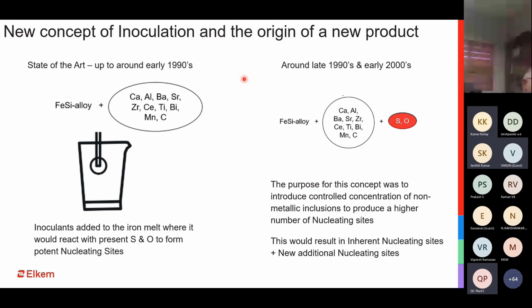But in the late 1990s or early 2000s, the concept of inoculants bringing their own sulfur and oxygen came into the picture. The concept was that we add sulfur and oxygen along with our basic inoculating elements into the system, which acts as a non-metallic inclusion. Because the sulfur and oxygen is there, it would combine with its own inoculating element to give you nucleating sites. And these nucleating sites, along with the already available nucleating sites in the iron, will give you a much better nucleation. And better nucleation means more nodule count. It means much better casting homogeneity. It means much better control on shrinkage, much better control on carbides.